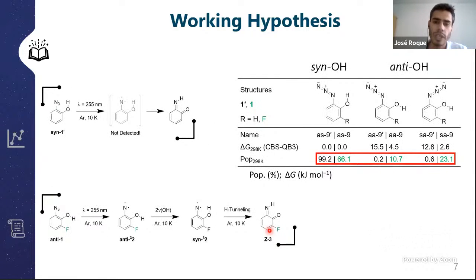And we also did some early calculations at the CBS-QB3 level for both azides. And what the calculations predict is that the Boltzmann distribution for the non-fluorinated derivative here in black predicts that 99% of the molecules should adopt the syn-OH conformation. But when we introduce the fluorine atom, there's more or less 30% of the molecules here in green that should adopt anti-OH, which are the ones we are interested in. So this seemed like a very promising system.